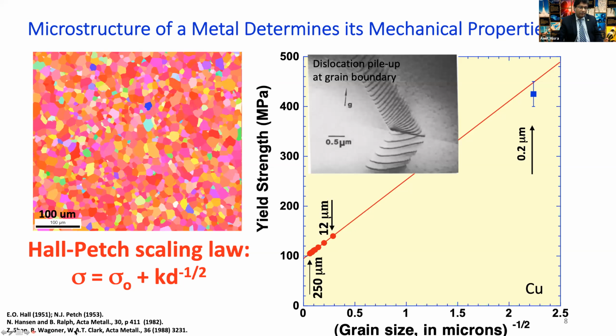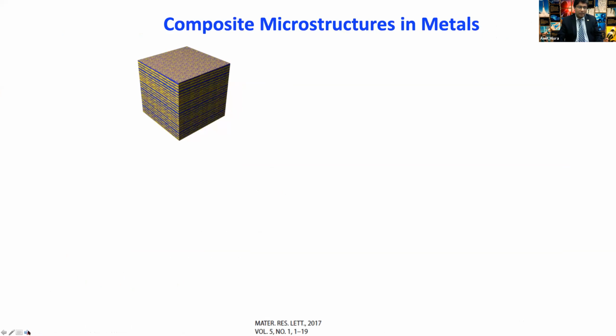And the reason for that is based on dislocation theory, that crystals deform by moving dislocations on crystallographic planes. And dislocations tend to pile up at grain boundaries because there is a crystallographic misorientation. And so the smaller the spacing between grain boundaries, the stronger the material becomes, because the grain boundaries are obstacles for shear or glide of dislocations. So this idea has been used to refine microstructures to increase the strength. But of course, there are limits to what one can do with this.